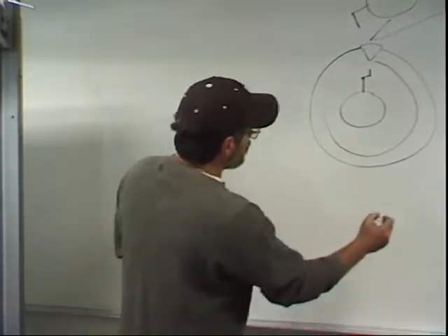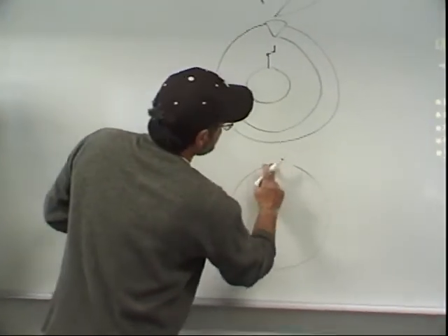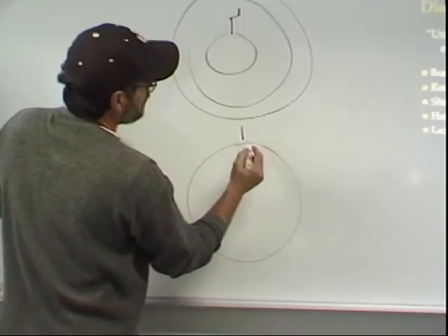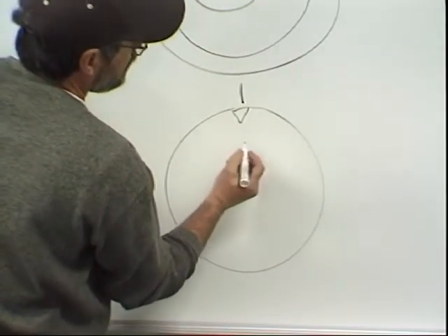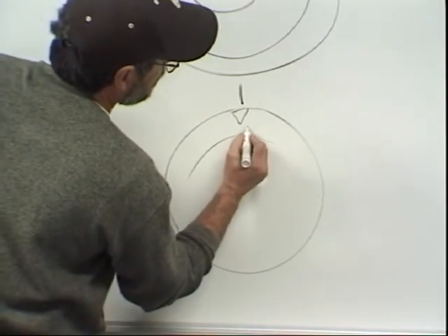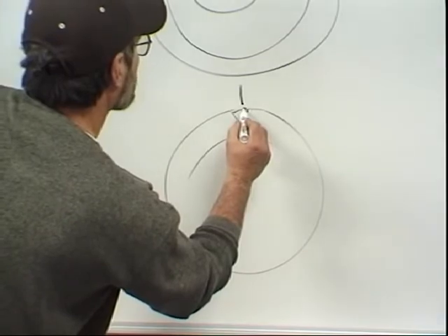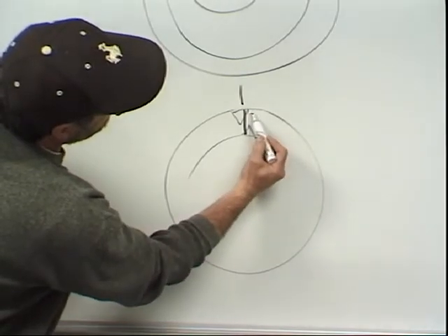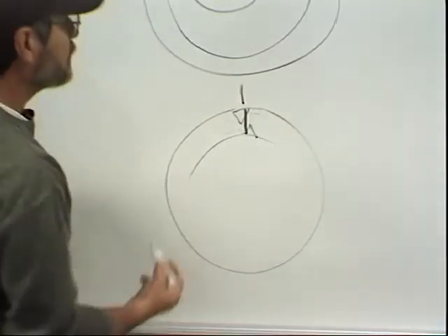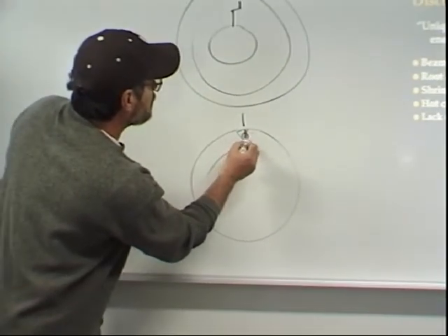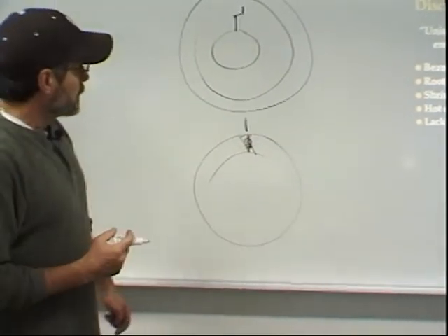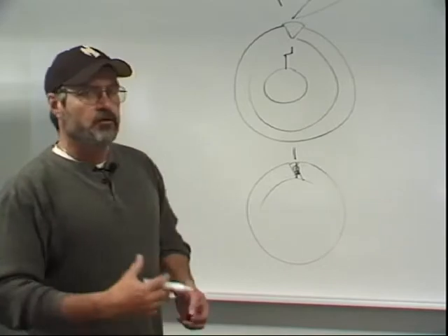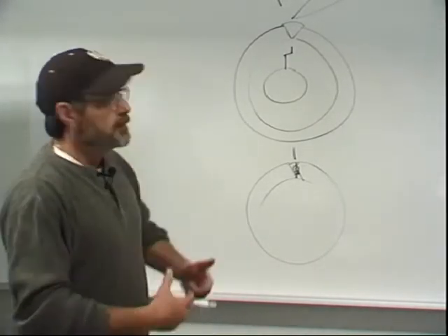Well, the problem was misalignment. What happened was as this one was coming down here, it was creating a weld like this, and as this one was going in here, it created a weld like this. And the joint was a square butt joint that ran down like this. And so you can see that the top one caught a little bit here and sealed it. The bottom one caught a little bit here and sealed it, but this whole big section in here, there was no weld metal. So it was strong enough to withstand 110% of the working pressure during the pressure test, but once it got put into service, it failed.